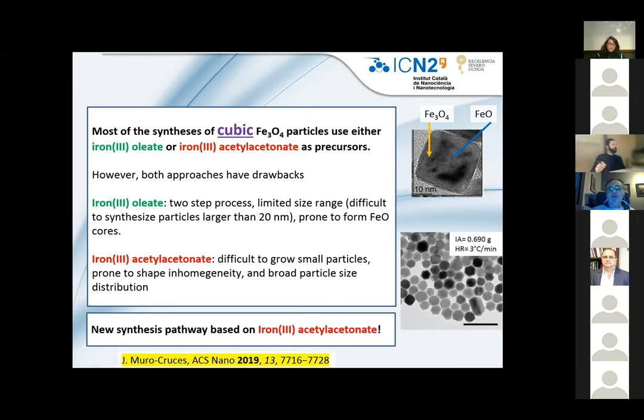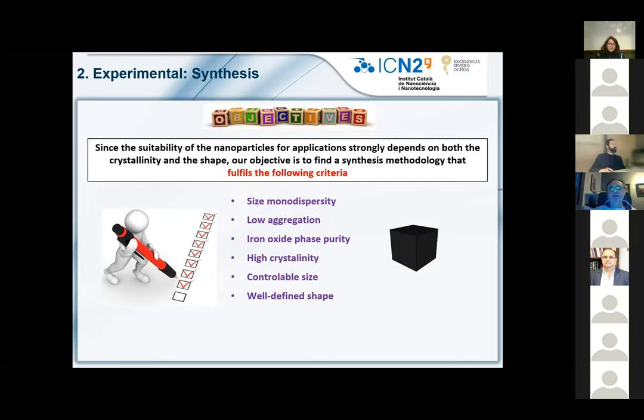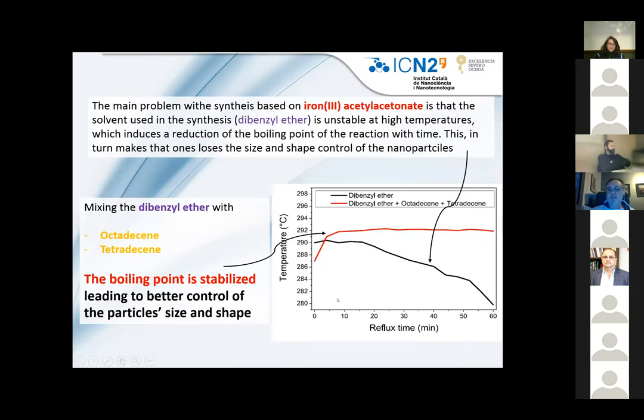This approach is prone to shape inhomogeneity and broad particle size distribution. Here I show you an example where you have many different types of particles when using iron acetylacetonate. So what I'm going to tell you today is a new synthesis pathway based on iron acetylacetonate. Since the suitability of nanoparticles for applications depends both on the crystallinity and the shape, our objective is to find a synthesis method that fulfills the following criteria: that the particles are size monodisperse, have low aggregation, have a pure iron oxide phase, have high crystallinity, and have controllable size and well-defined shape.